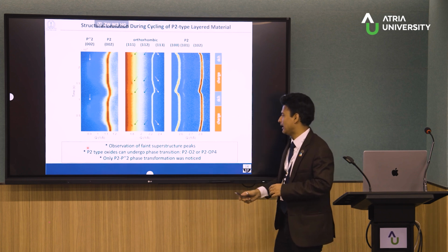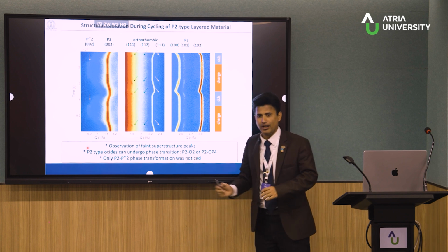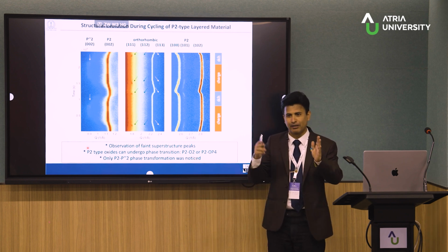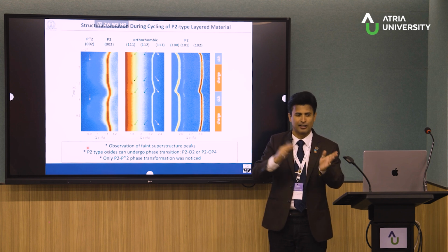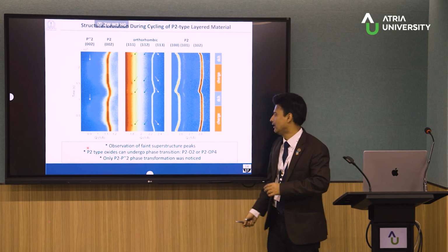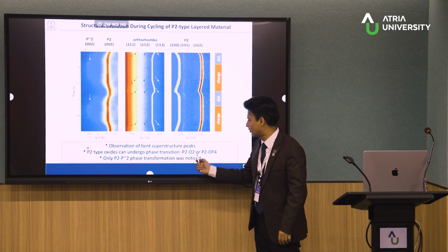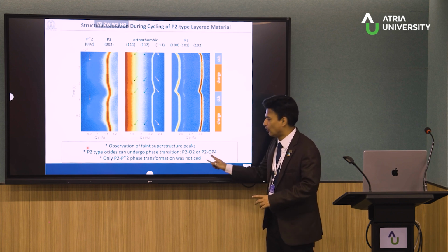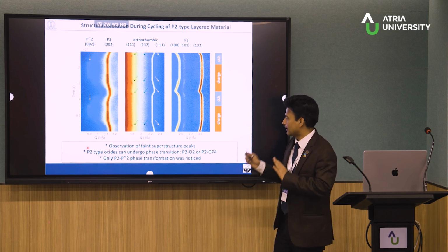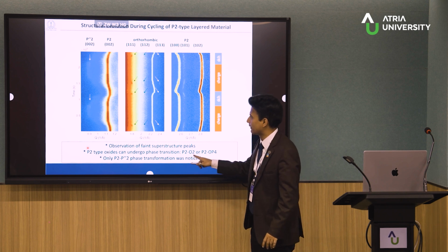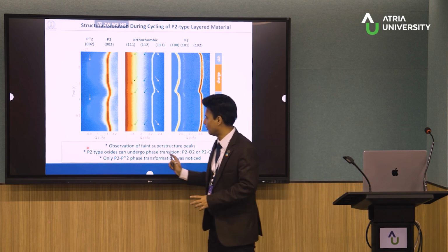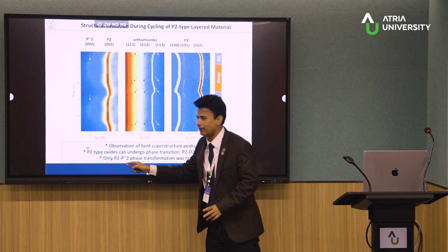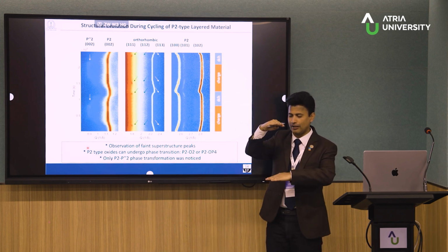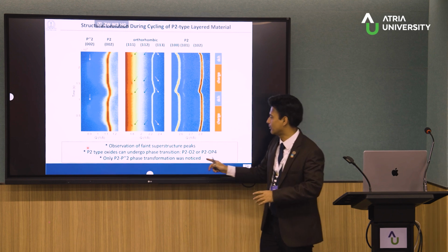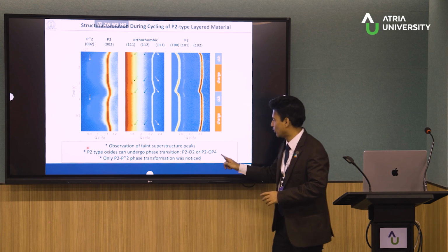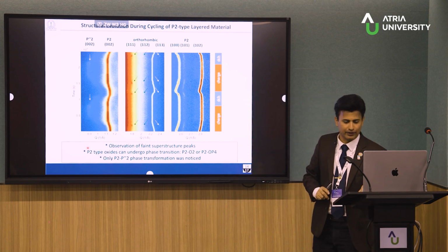When you go to high voltage, it changes from P2 to O2. Once the prismatic becomes octahedral, it is irreversible, it will not come back, and the cyclic stability will be bad. So you want to avoid this P2 to O2 or P2 to OP4. No O, only P. In our case, luckily, we are not getting any O2 kind of phase. So there is no peak because of O2, only P2 and P double prime 2. So P2, or a sudden change in the interlayer distance. We are avoiding this O2 kind of phase formation, which is good for us.